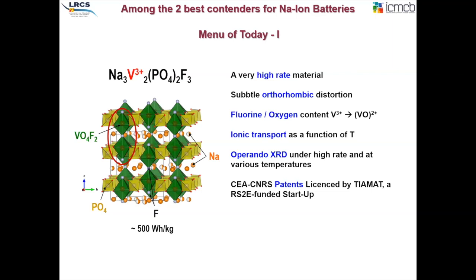I will show that the crystal chemistry is really fascinating, and we discovered a very subtle orthorhombic distortion that is indeed important to qualify the material and to qualify the stoichiometry. And in particular, as I will demonstrate, the oxygen versus fluorine ratio in this compound plays a very important role. As you will see, this is a pretty fast ionic transport compound, and this leads to a very important property when it is used in a sodium battery, which means the power capability of the cells that will be built on NVPF. We made operando X-ray under different conditions, at different temperatures and at different C rates, to show indeed that it has really exceptional properties. And not to mention that around NVPF, there are several patents and licenses that have been taken by the Tiamat company in particular, with many patents made in France through the RS2E network and with the CEA.